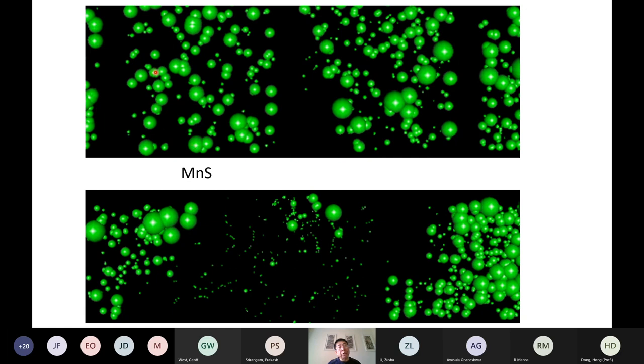So this shows the sample without electropulse treatment. All the manganese sulfide inclusions are distributed almost uniformly across the space. However, if we have electropulse, then after treatment, at this central part, inclusions almost disappear, and at the surface part there are a lot more inclusions.